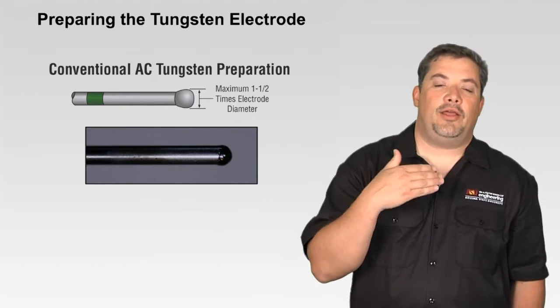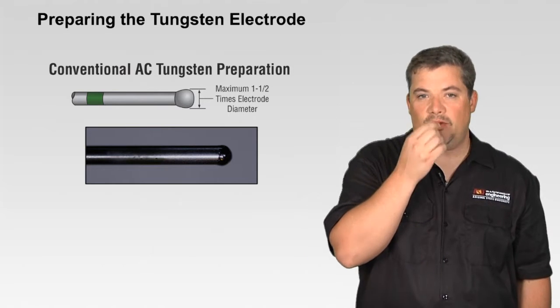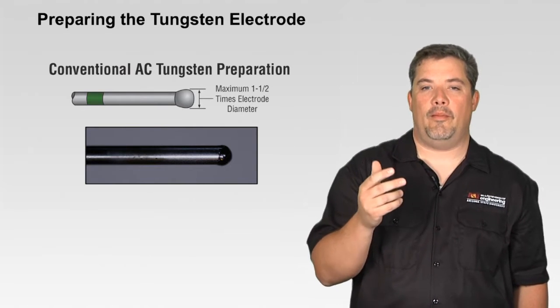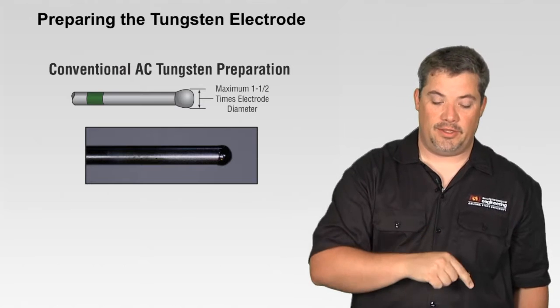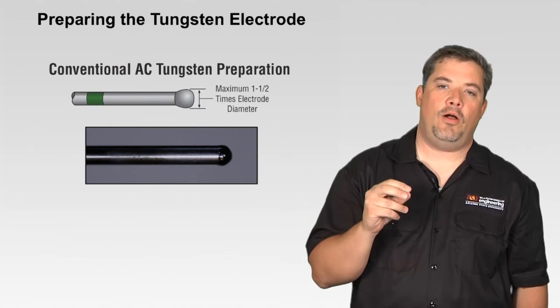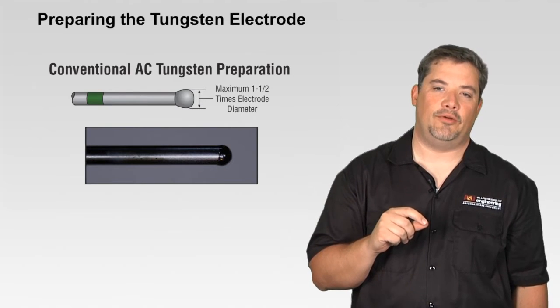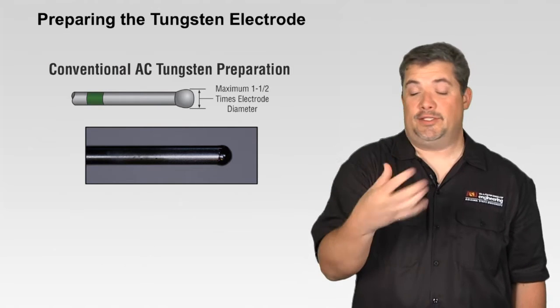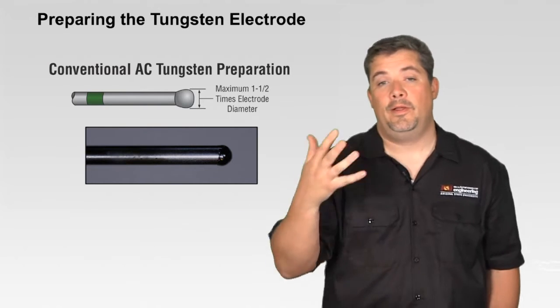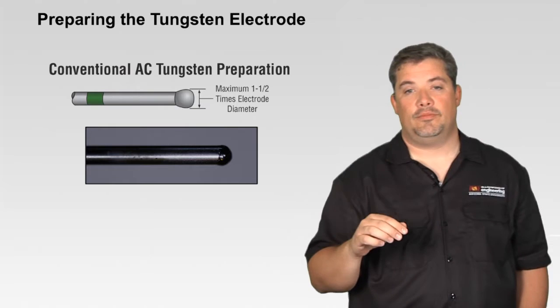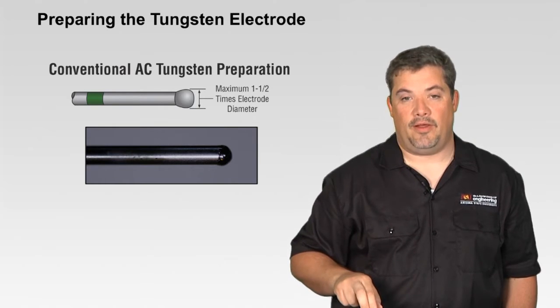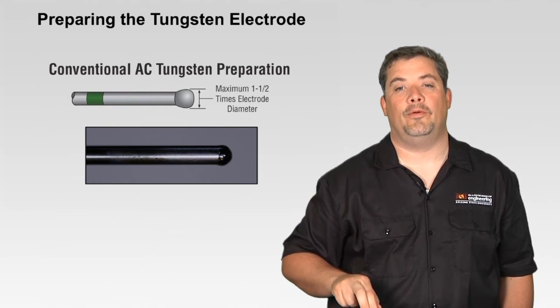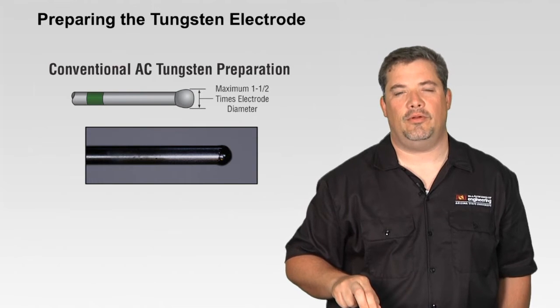So when we're doing conventional AC TIG, we prep our tungsten where it makes a ball. A pure tungsten, you can see the green in the image. That ball shouldn't get any more than 1.5 times the electrode diameter. If it does, it'll actually get so liquid, it'll drop out into the puddle. Now you have a tungsten inclusion. So from the image, you can see the photograph is what typically happens in about a safe spot to keep it.